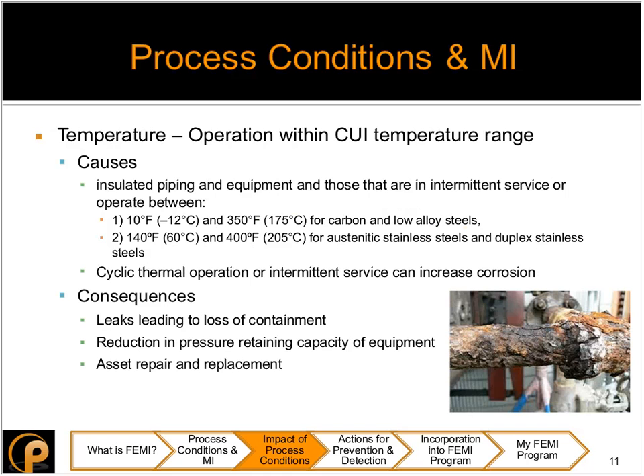Now, some of the causes for CUI are insulated piping and equipment operating in temperature ranges between 10 and 350 degrees Fahrenheit for carbon and low alloy steels, and between 140 and 400 degrees Fahrenheit for stainless steels and duplex stainless steels. It can also happen in equipment that has cyclic thermal operation or is in intermittent service. As a consequence, like I described earlier, it can cause leaks leading to loss of containment. It can also cause metal loss on your equipment and piping, so you might have to re-rate, or derate, your equipment, which reduces its pressure retaining capacity.